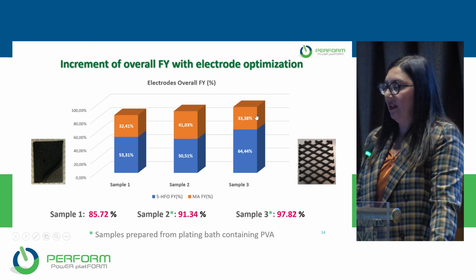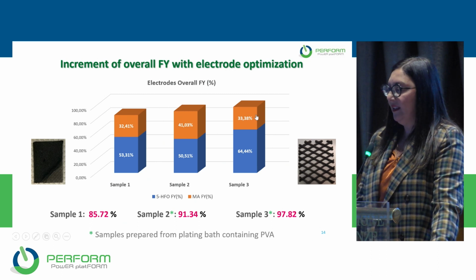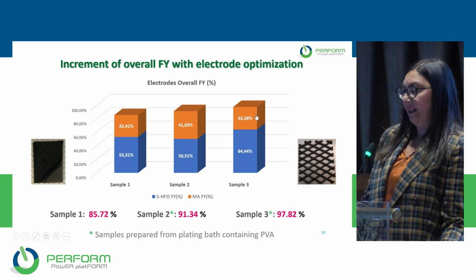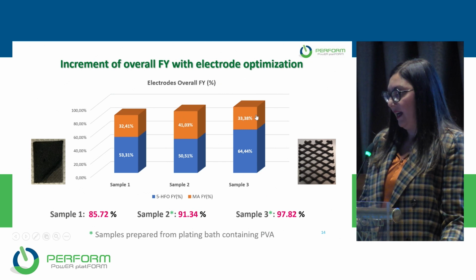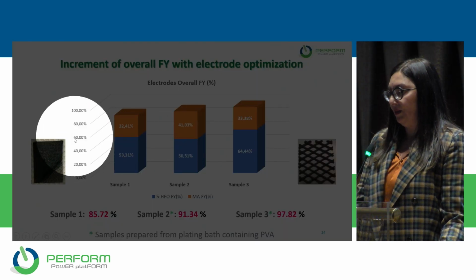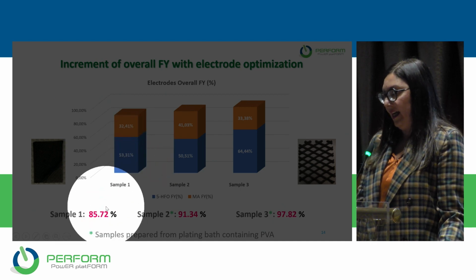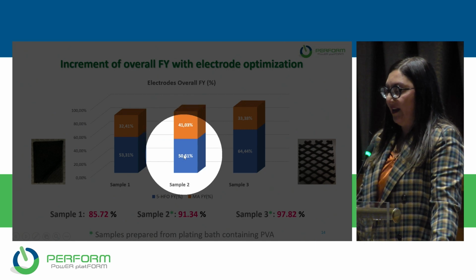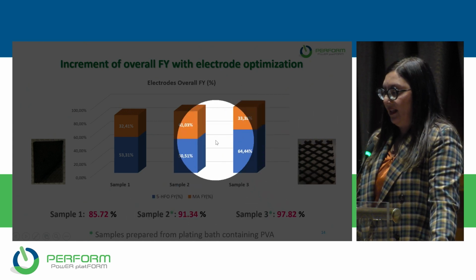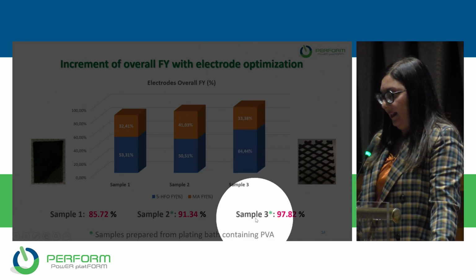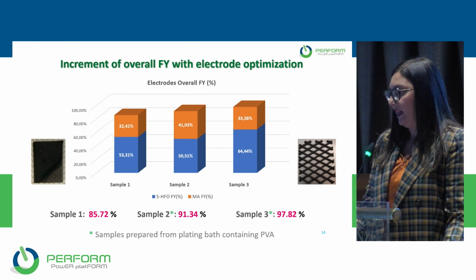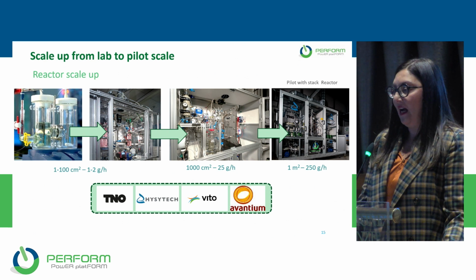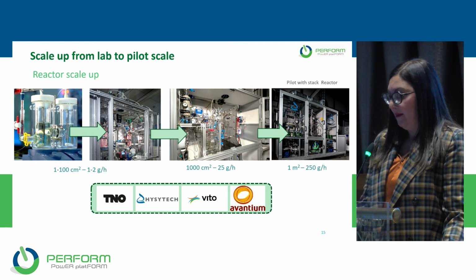All this optimization can be observed in an improved overall Faradaic yield with electrode optimization. In fact, here I reported the first electrode I showed you, with a Faradaic yield of 85%, more or less. Modifying the plating bath with the PVA, we obtained an increase in Faradaic yield, and we also modified the support and stability of the system. We obtained a higher Faraday yield. At the end, this type of material was suitable for the upscale that was realized by the other partner of the project.